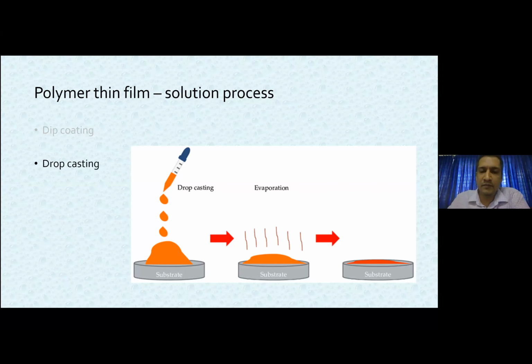So this problem is due to the differential evaporation rates at the edges compared to the center of the drop. Since the solution has a tendency to resist concentration thermodynamically, the solvent moves at a faster rate towards the edges if the evaporation is faster at the edges compared to the center. Due to that, it also carries the dissolved solute along with it, and then it slowly deposits over the ring. This is how we get a deposition as a coffee ring.